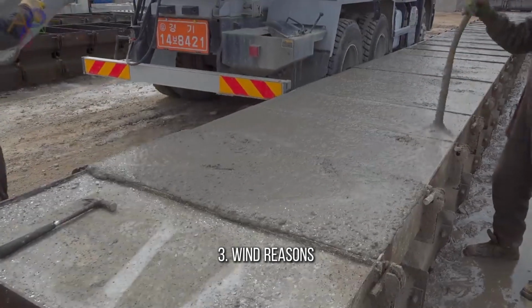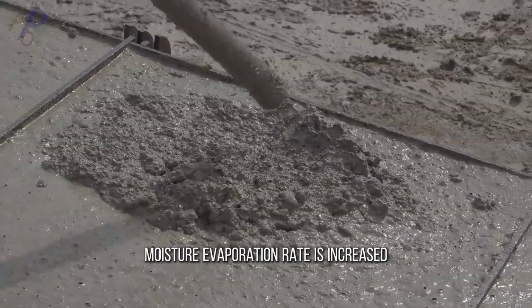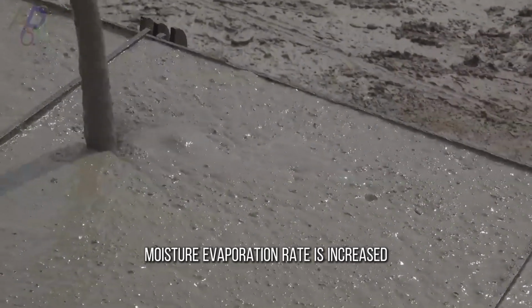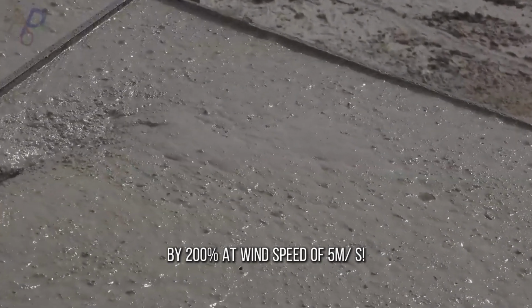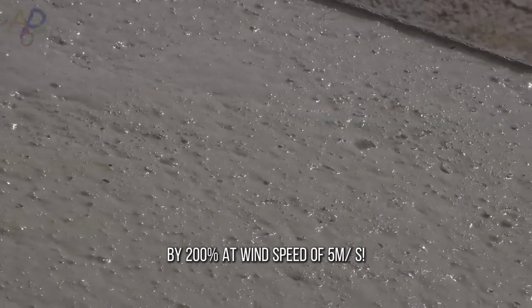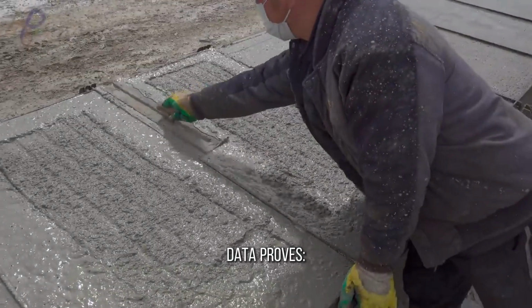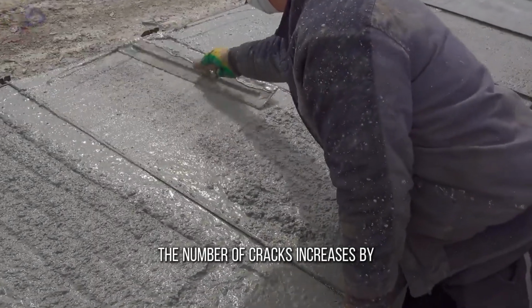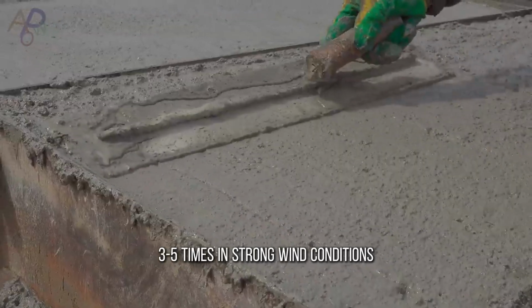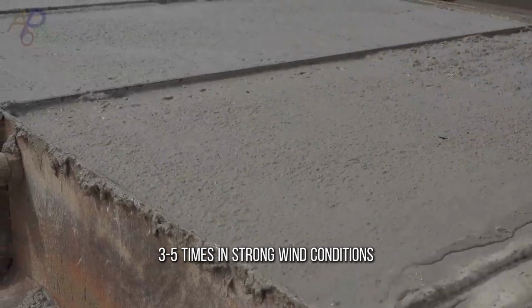Three, wind. Moisture evaporation rate is increased by 200% at a wind speed of 5 m/s. Data proves the number of cracks increases by 3 to 5 times in strong wind conditions.